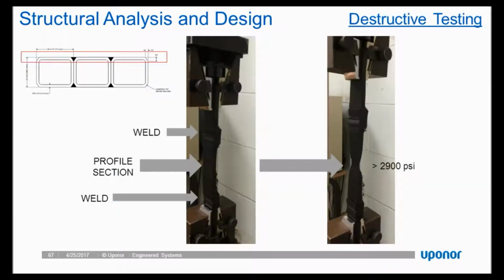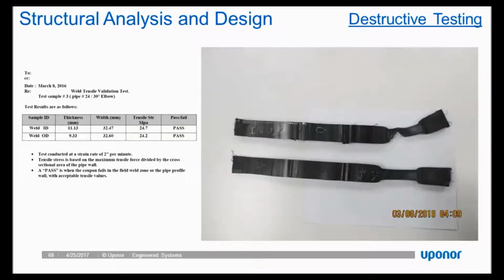As I mentioned earlier, during our thermoplastic welding discussion, destructive testing is part of our quality control program. But this also reinforces what I said about the weld seam being the strongest part of the material. Here you can see a 3-profile rectangular section, and the red box represents the coupon sample that was taken out of it. We turned that vertical, put it in a tensile strength test machine, and applied 2900 PSI to it. You can see the weld at the top there and the weld at the bottom, and then the profile section between it. As we would expect, the profile section is the first thing to fail under that pressure, and that confirms that our welds are strong and is in line with our quality control program.